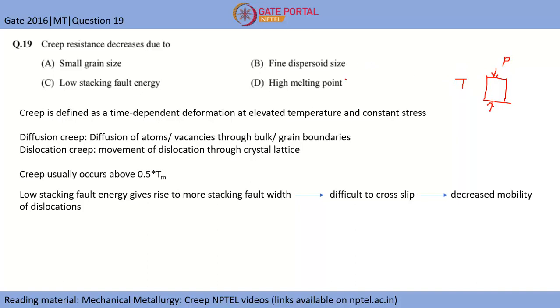And creep is of two different types: diffusion creep and dislocation creep. In diffusion creep, diffusion of atoms takes place from one region to another. There are three modes of diffusion: through bulk, through grain boundaries, and surface diffusion, which we are neglecting here. So two are the major diffusion mechanisms by which atoms or vacancies can migrate from one place to another. The second one is dislocation creep, which occurs by movement of dislocations through the lattice, causing strain in the structure.